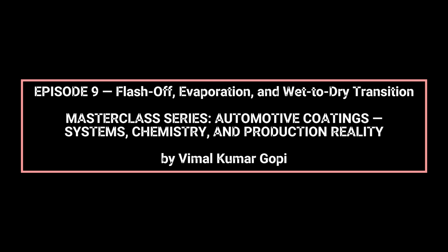The wet-to-dry transition represents the point where solvent loss causes a rapid increase in viscosity, transforming the film from a flow-dominated system to a diffusion-dominated one. This transition defines the final film structure. Once crossed, defects introduced earlier cannot self-heal, and any trapped solvent becomes a latent failure risk.